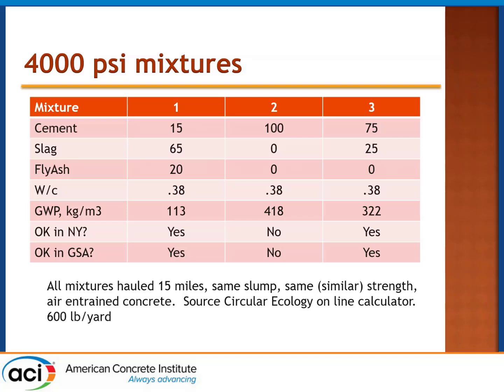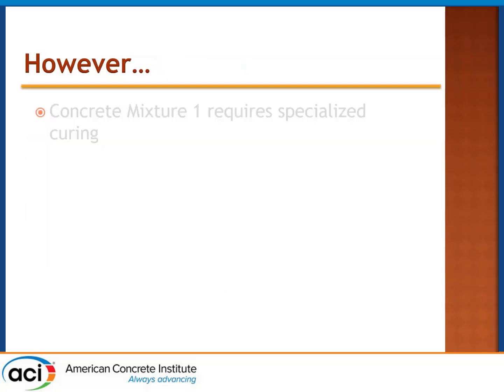That first mixture will be 10,000 psi at 20 days. However, it's purposely put up faintly so you don't have to read it. It requires specialized curing. If you cure it where it is not able to self-stoke, to self-anneal, to heat itself up to about 130 or 140 degrees Fahrenheit, it is not going to behave very nicely for the first 7 to 10 days. So if you're okay with curing the day or finishing tomorrow and maybe cutting the joints the day after tomorrow in your floor, that's no problem.